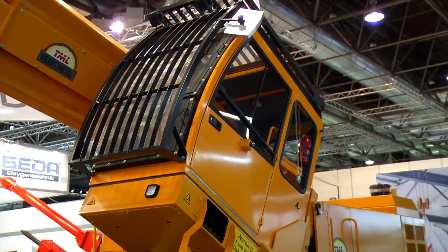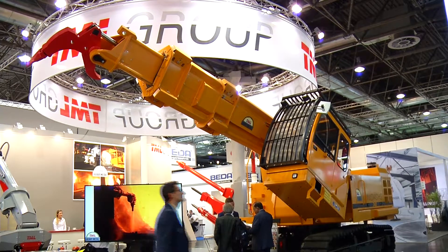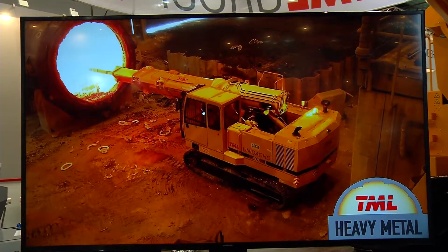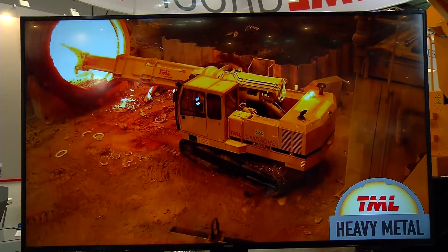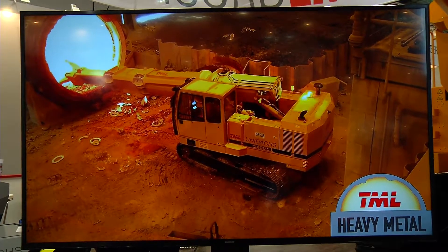We call them debricking machines, though some people like to call them telescopic excavators. The one behind me on the left-hand side is a 34-ton machine especially built for debricking furnaces and ladles after the refractories have been worn out, and also for cleaning them in absolutely hot conditions. We're talking temperatures somewhere around 1200 to 1400 degrees to remove the skulls — which is a build-up of slag and steel leftovers around the mouth and inside of the vessels — to make them clean again.